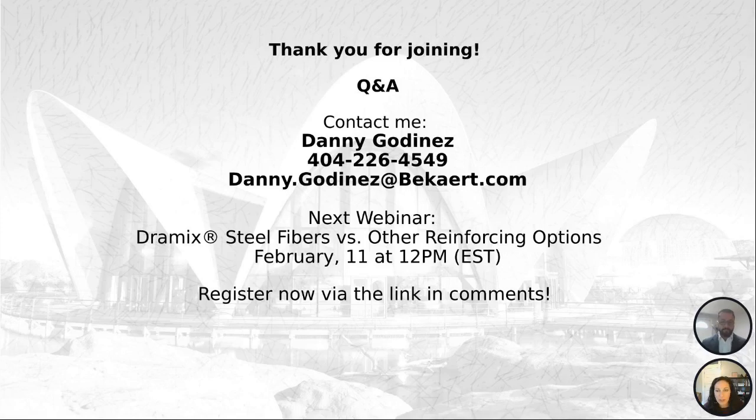Perfect. Next question is asking if there is a maximum dosage recommendation. Oh, that's a really good question. Yes, there is a point where the solution with a maximum dosage doesn't become cost effective anymore. So if a dosage exceeds, I would say, 32 kilograms per cubic meter, at that point we need to start reevaluating what would be the better thickness to make sure that we get better finishing results. So there is a correlation between thickness and dosage to be able to come up with the most optimized and cost-effective solution while allowing the contractor to have good finishing results.